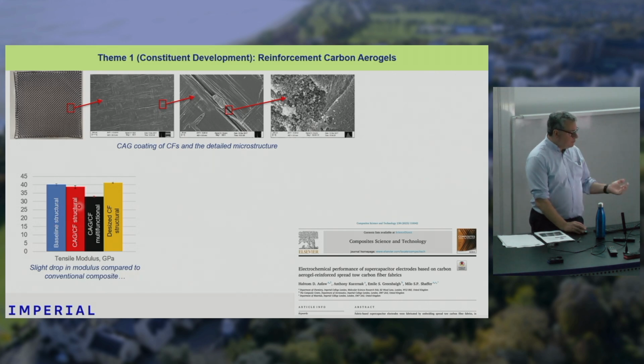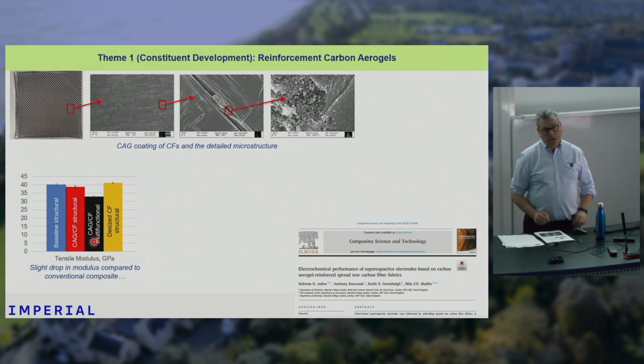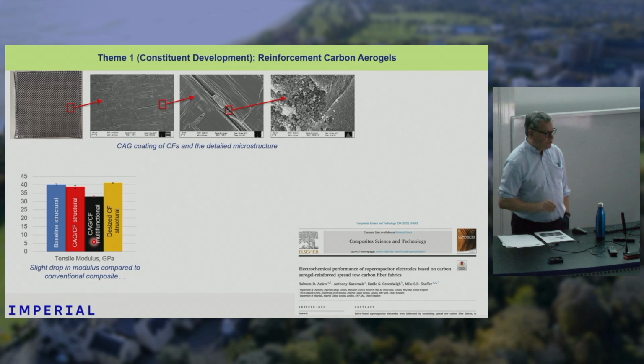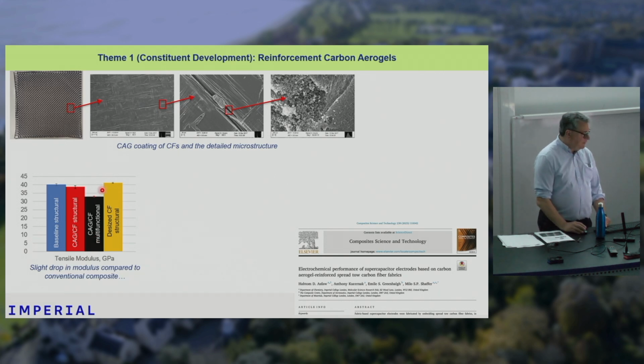This is a structural resin with carbon aerogel on the carbon fibers. So we're maintaining the same mechanical properties, modulus. If we use the multifunctional matrix, we get a drop because the multifunctional matrix, as I'll show you, is much softer. And then we did a desized version as a sort of control.